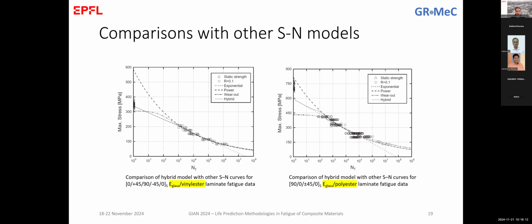And if we apply this model, we can see that the hybrid model is the one with the solid black line. And we see that to avoid the problems of the power law, for example, that overestimates this, in this case, we have our model here that changes the slope, follows the slope of the exponential model at the low cycle fatigue, and then at a certain point it switches and it follows the slope of the power curve.